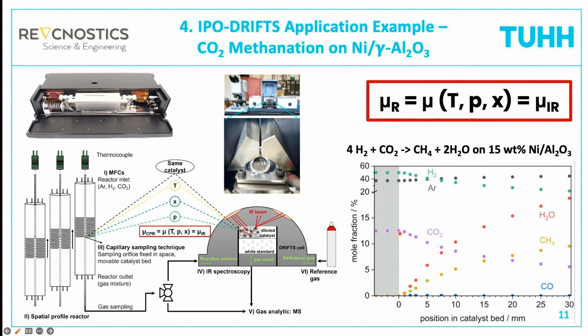And then our feed mixture hits the catalyst bed, and you see how the CO2 is converted. You see how the hydrogen is converted. You see the formation of methane. You see the formation of water, and you see there is a little bit at the entrance of reverse water gas shift where we get a little bit of CO, but not very much, almost 100% selectivity to CH4. You can even, when you look carefully, see the contraction of the moles because our internal standard argon is going up in the mole fraction profile. So this is what the compact profile reactor gives you.